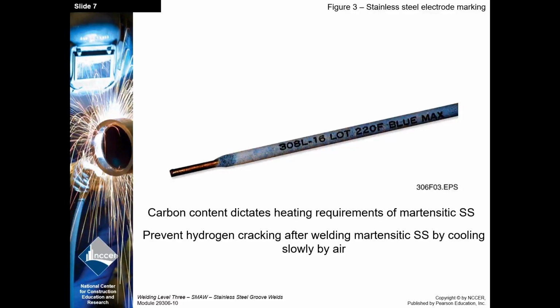Prevent hydrogen cracking after welding martensitic stainless steel by cooling slowly in air. So what happens? In the heat-affected zone, hydrogen diffuses. It's pulled out of the air, gets into your weld pool and hangs out. Now, if you cool it quickly, that hydrogen has to get back out to the atmosphere as this cools. If you cool it slowly, the hydrogen has time, so it doesn't come out of your weld forcefully. But if it cools quickly, it's going to crack. You're going to get hydrogen cracking, underbead cracking caused by that.